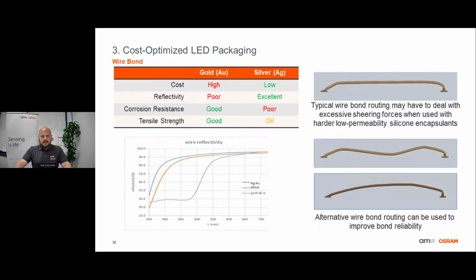Now, silver, with its superior reflectivity, can actually increase the LED's flux by as much as 2%, while lowering material costs by up to 70%. However, again, the trade-off is the tensile strength is approximately 15% lower. Because of this trade-off in tensile strength, combined with the hardness of the low permeability silicones, as I just mentioned, careful attention needs to be made to prevent wire bond breakage due to thermal cycling. So in this case, alternative wire bond routing or looping can be used to improve the reliability for wire bonds. And you can see on the right side here what you would see as a traditional wire bond routing versus some alternative options to help reduce those issues.